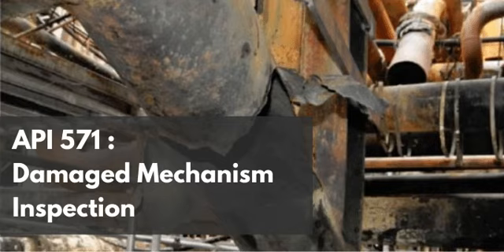The very presence of that up to 10% ferrite phase, which was intentionally designed into the weld to keep it structurally sound on day one, is the exact critical factor that actively invites 885 degrees Fahrenheit embrittlement over the next 20 years. That is just wow.